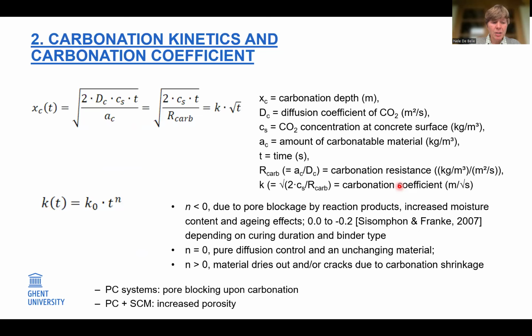Now, as the carbonation reaction proceeds with the square root of time, the first equation here assumes a steady state condition. However, like mentioned, if carbonation reaction products block the pores, and because of continuing hydration, the carbonation coefficient, K, could actually decrease with time. And then in the second equation here, you would have a negative exponent n. On the other hand, n could be positive when the material is drying out or it cracks due to carbonation shrinkage. And that is often what we see in the case of concrete with supplementary cementitious materials.